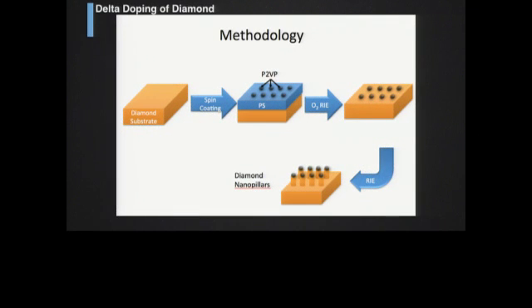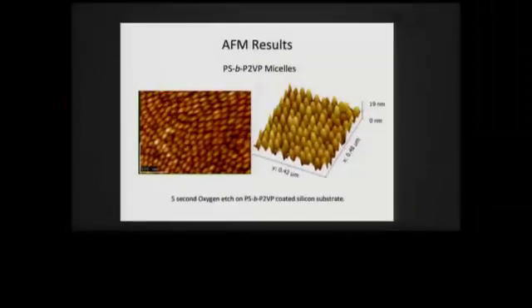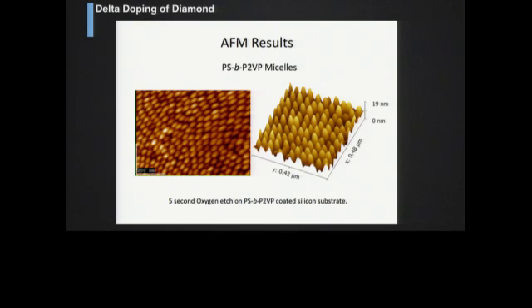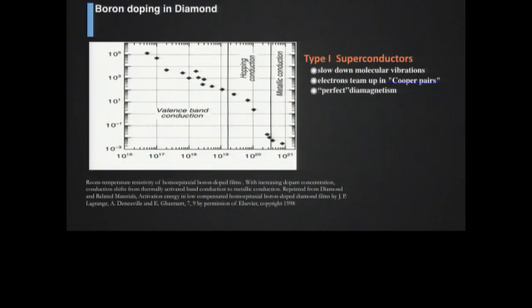So the process is sort of like this. You start out with a diamond substrate, you spin coat the diblock copolymer on it. You activate the diblock copolymer, typically either with UV light or temperature, and then you do reactive ion etching, and then you're left with the diamond pillars. So these are some samples after we've done the reactive ion etching of them.